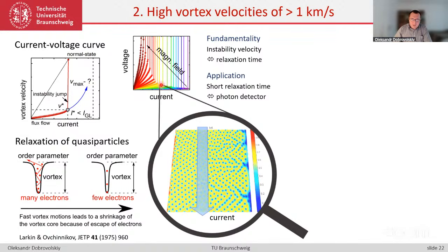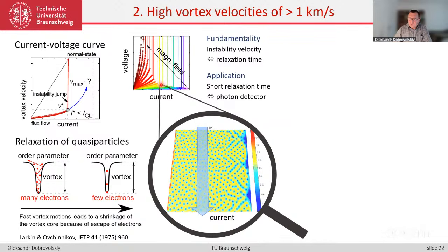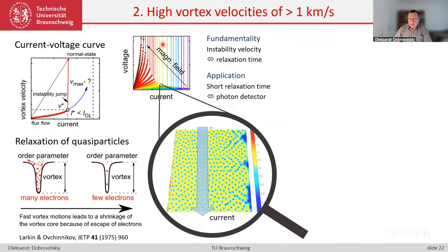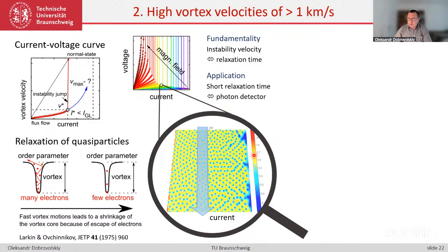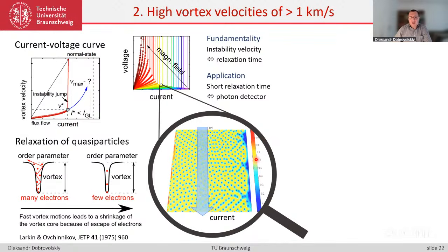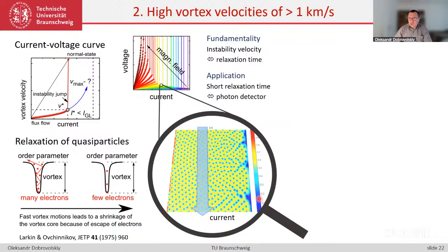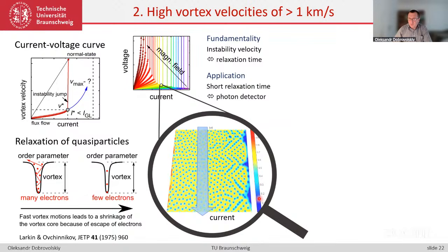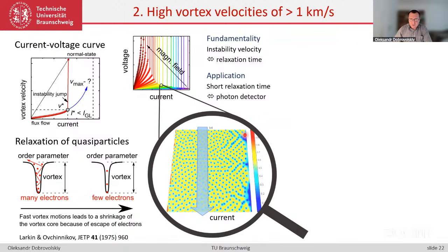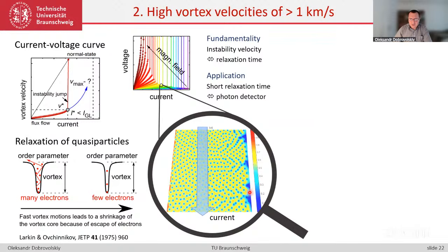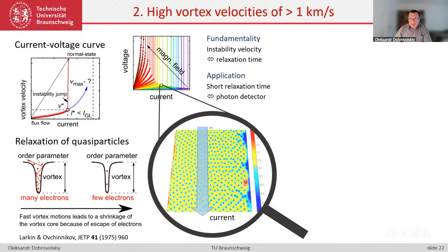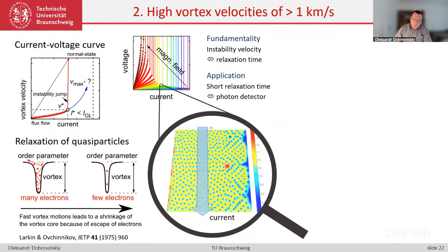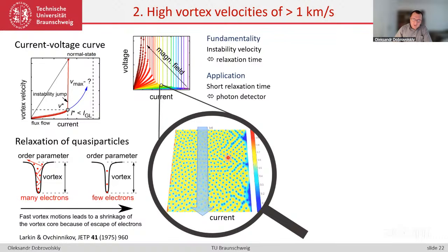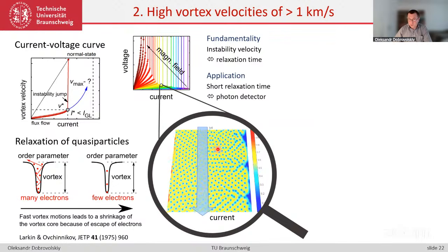So at this last resistive point in the flux flow state, before the jump to the highly resistive state, these are results of time-dependent Ginzburg-Landau modeling. You see that the blue color corresponds to the nucleation of the normally conducting phase. So basically, superconductivity is destroyed first at the edge, where vortices enter the sample. And you see here already a deviation from the expectation of a perfect vortex crystal. You see that long-range order is lost here.